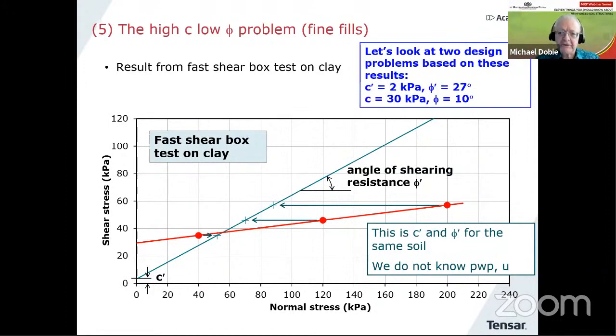So to help convince people, I'm going to show you the results of designing a reinforced soil structure for two sets of strength data. They're the two you see there. We're going to use C' of 2 kilopascals and phi' of 27 degrees, very typical for a fine soil. And then we're going to use the C of 30 and phi of 10 degrees. I purposely leave off the dash because those are not effective stress strengths. We'll look at the effect those two sets of strength properties have on the design.